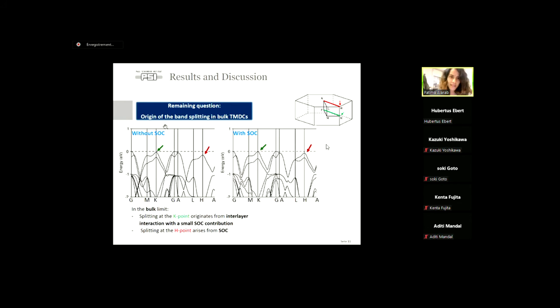So those are basic calculations for molybdenum diselenide without and with spin-orbit coupling. And if we look closely at the K point, with and without spin-orbit coupling, we have a splitting that increases slightly when we add the spin-orbit coupling. But at the H point without spin-orbit coupling, there's no splitting. But then when we add the spin-orbit coupling, we have a splitting of the bands.